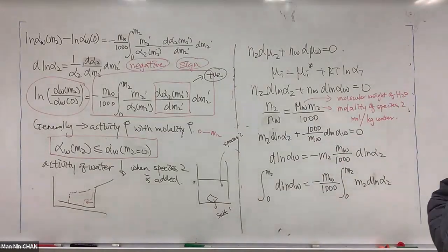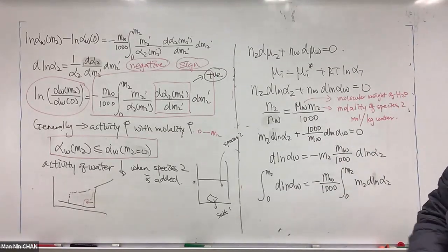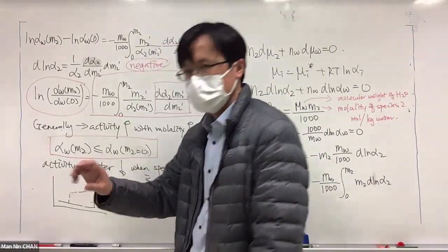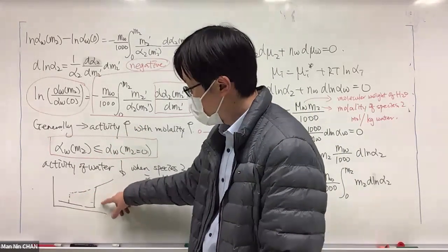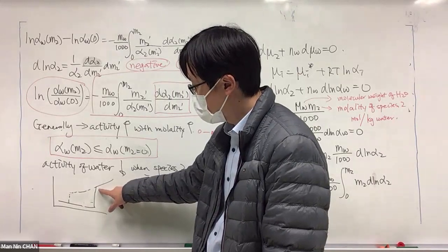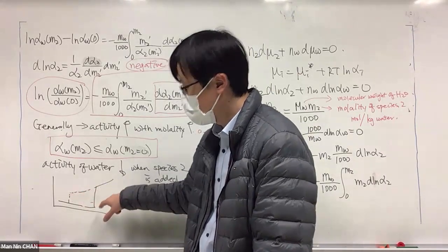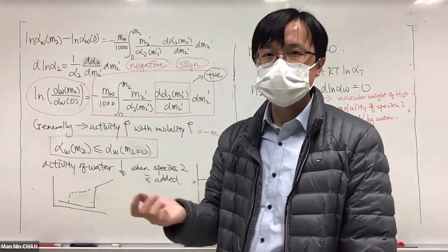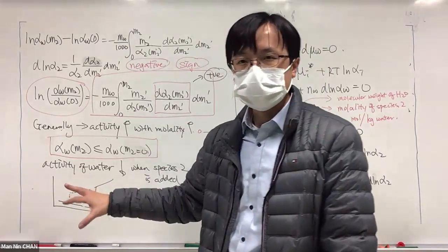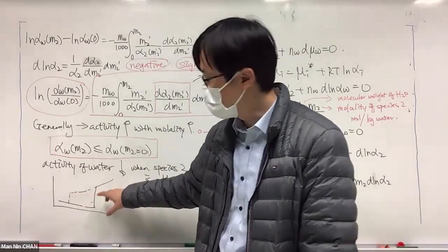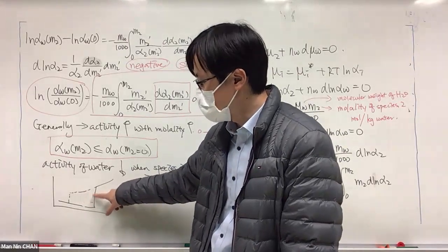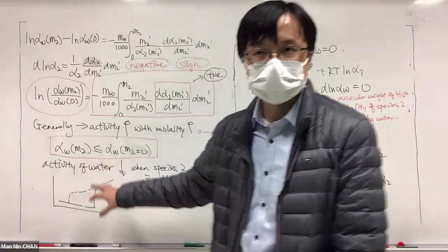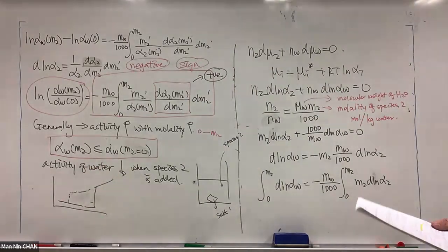So I think the key message for this one is, when you have a single species, if this species exhibits a sharp phase transition, say in this case, a sharp deliquescence process and also a sharp crystallization process, usually you only observe this for a single component, a single species. In case your system has multiple species, usually you will not see a very sharp phase transition like this. You will see multiple steps, something like this.